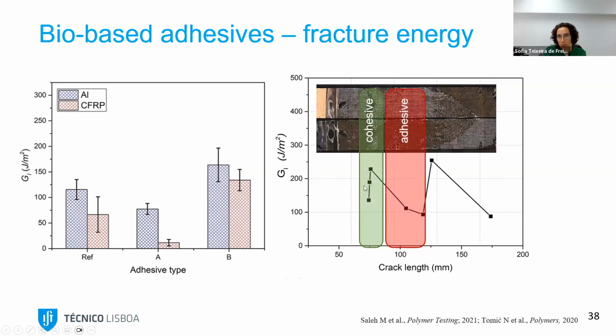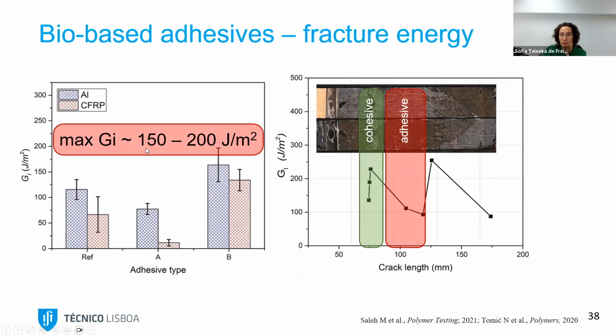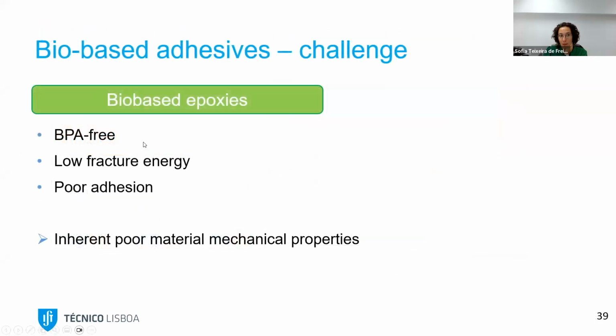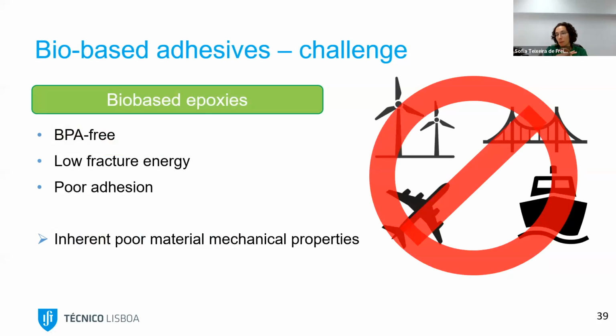What we see is that we have both cohesive failure and adhesive failure. But even when we have cohesive failure, for different combinations of the tannic acid, we got a maximum energy release rate of 150 to 200 joules per square meter. This, if you remember, is one order of magnitude lower than the one we were using for aerospace structures, which was 2000 joules per square meter. So these bio-based adhesives, which are BPA-free, have a very low fracture energy, and they also have poor adhesion. They have inherently poor mechanical properties. So there is no way that, with these properties, they can be applied in load-bearing infrastructures, because they simply cannot compete. It's too low.